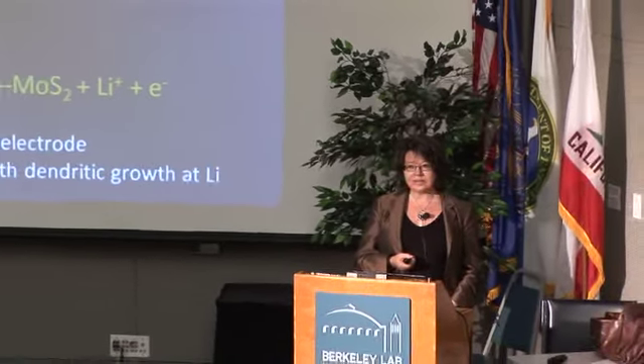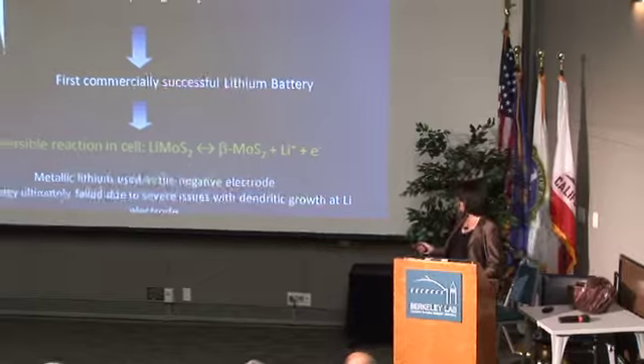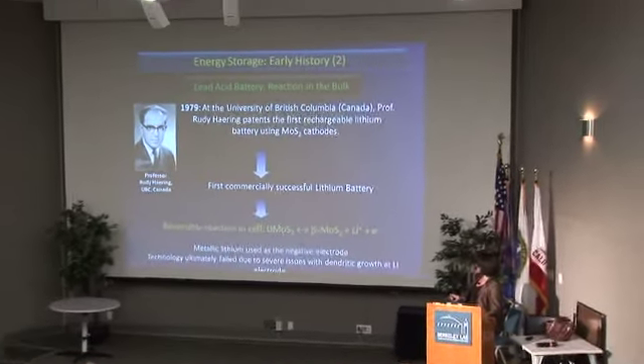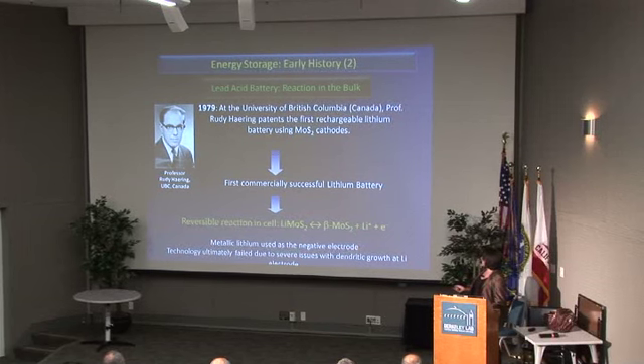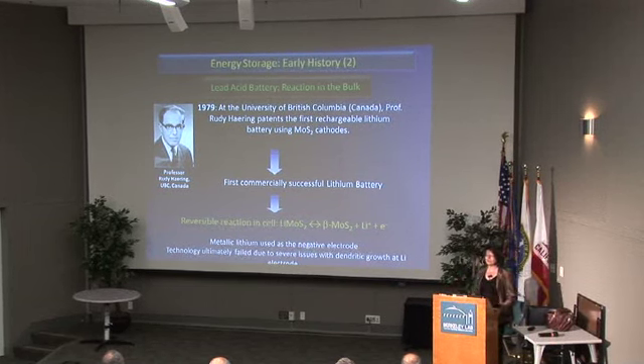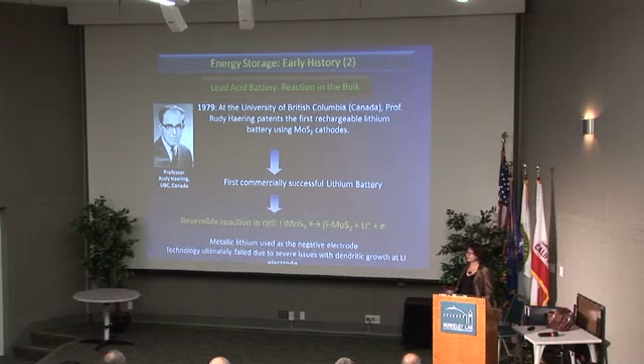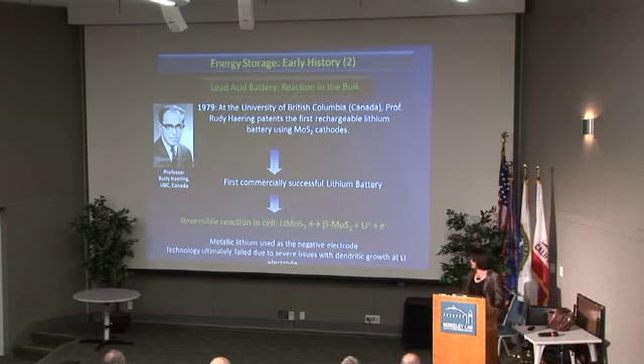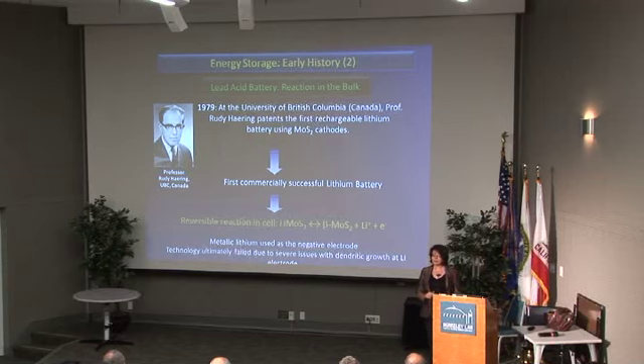And it was based on a reversible reaction in a cell, which involves a nice cheap material, molybdenum sulfide, and one can then use this as the positive electrode. It will react with lithium, and when it is delithiated, it forms a highly conductive form of the molybdenum sulfide. So the starting material is actually a semiconductor, and this reaction changes the phase and turns it into a great conductor by processes that are understood by solid-state chemistry. And it was this then that really started this company. They used metallic lithium as a negative electrode because they didn't know any better in 1979, and ultimately the technology failed due to problems with dendritic growth of that metallic lithium negative electrode.